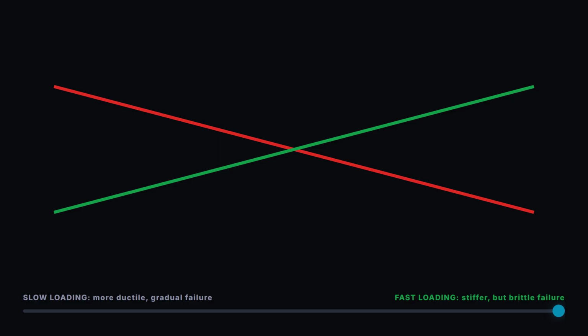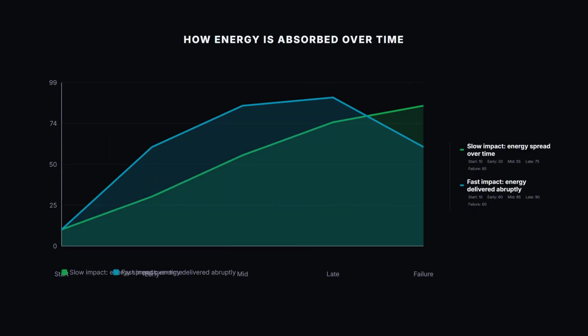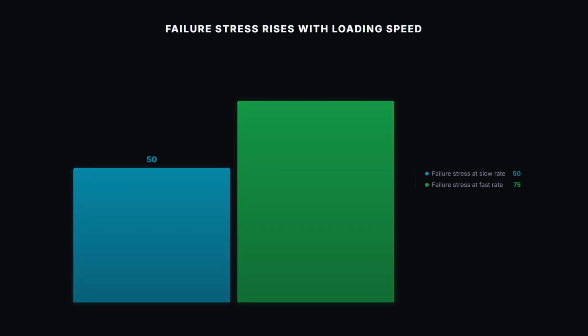The physics reason comes down to time. At low strain rates, microcracks have time to form throughout the material and dissipate energy across a wider area before anything gives way completely. At high strain rates, there simply isn't time for that same energy spreading process, so the bone reaches its failure stress with less overall strain, meaning less bending before it breaks. Laboratory testing on human cortical bone confirms this pattern precisely. As loading rate increases, the failure stress bone can withstand actually goes up, while the strain, or how much it stretches before breaking, goes down. Stronger in the instant, but with far less margin for error.